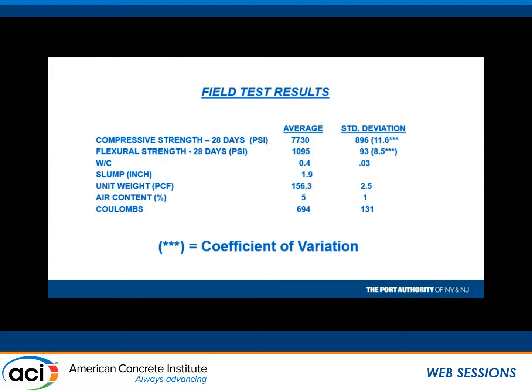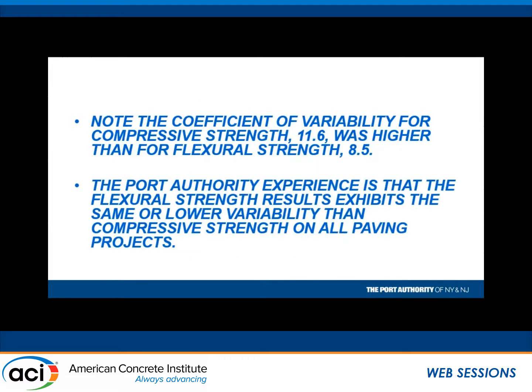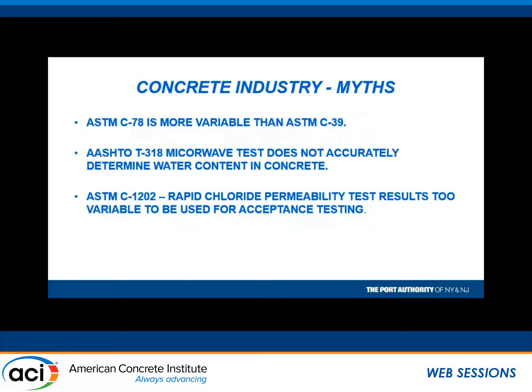So what gives here? What gives? How did that happen? Look at the water-cement ratio. Water-cement ratio there is what we got by doing a microwave test. Look at the standard deviation, 0.03. That's not too tough to take, is it? I don't think it is. And the air content and the coulombs, of course, were not an issue. So I think it was a great job. And again, what was interesting here, I think, is that the variability in the C39 test was higher than the C78 test.